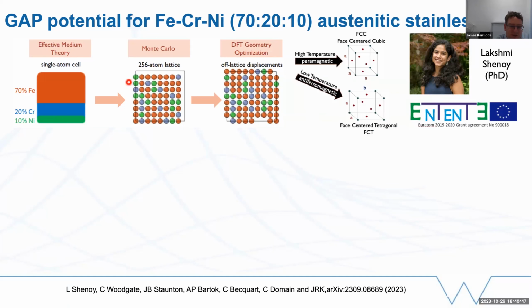So we're interested in this 70% iron, 20% chrome, 10% nickel system. We can build model systems with the correct short-range ordering using effective medium theory. I'm not going to go into that in too much detail, but you can have a look at the preprint link below on the archive if you're interested. We can evaluate them with DFT, and we can build reference configurations to build a model.